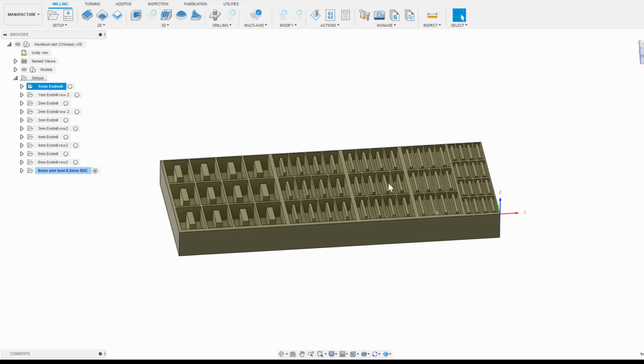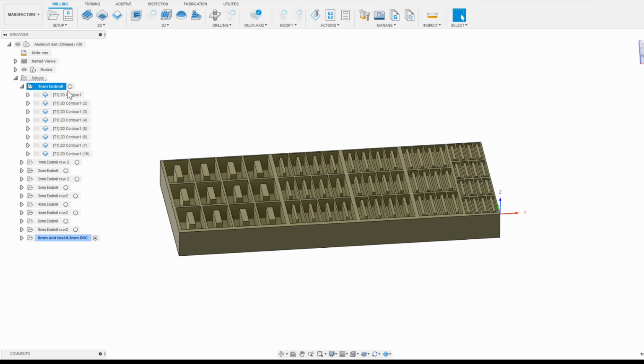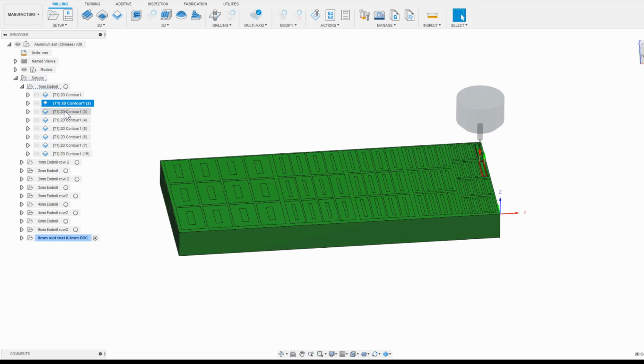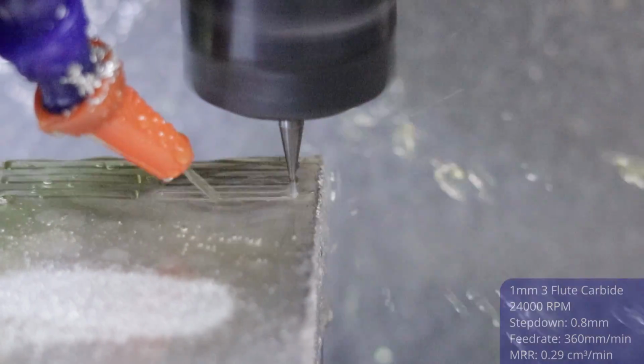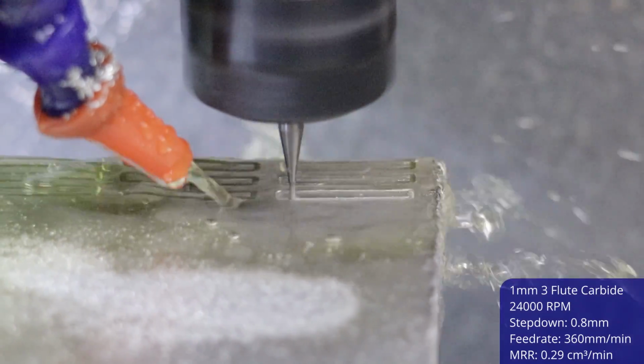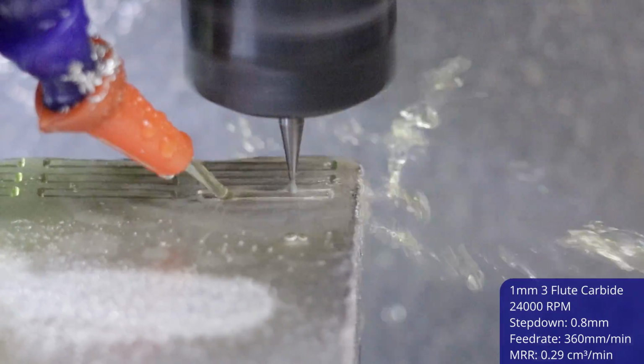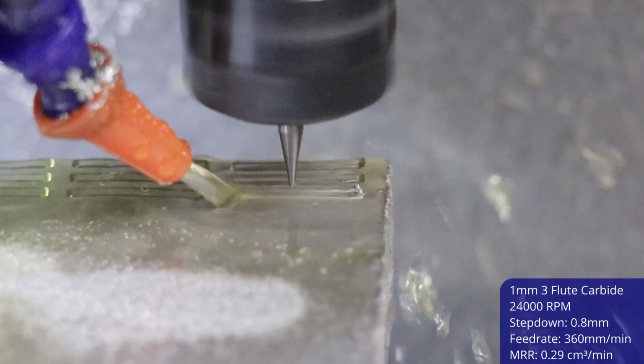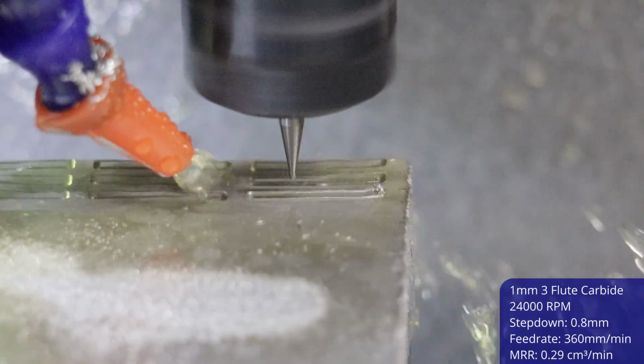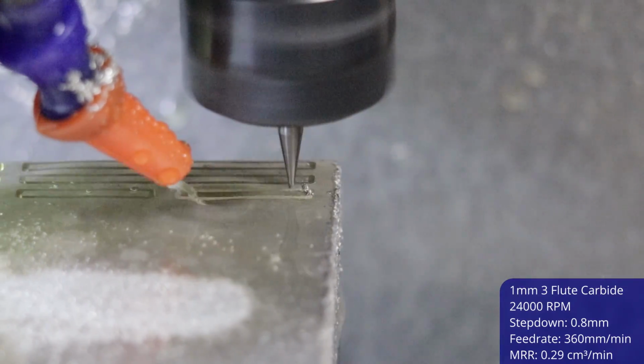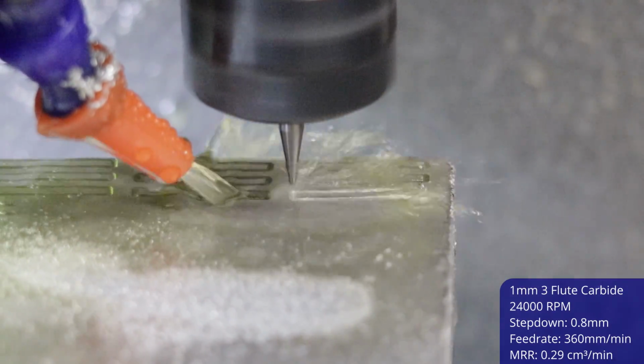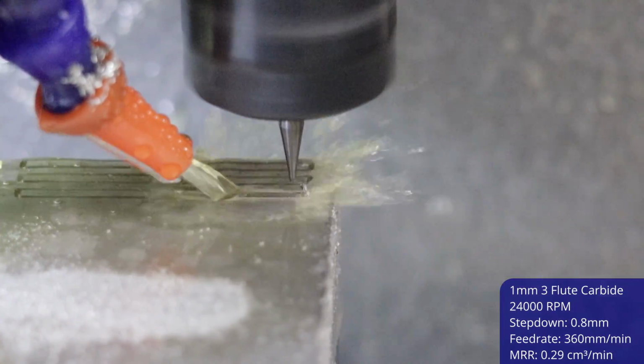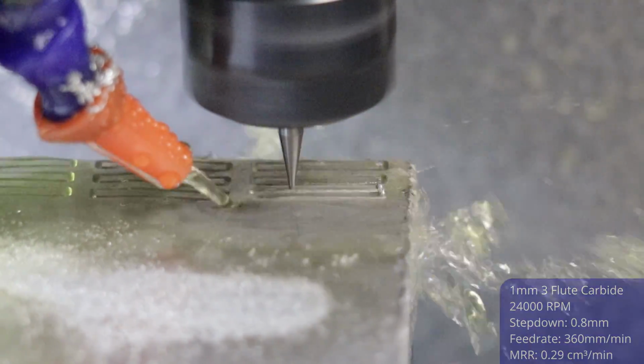I started off with a chunk of aluminum, and I did a bunch of test slotting with each of the smaller end mills. Again, I'll show you basically the final results of how hard I could push the tools and the machine. I am running the tools a little higher than the recommended surface speed, but they seem to be holding up fine. So with the 1mm tools, not much to see or hear again, and the tools break without a sound, so you really need to be careful not to feed them too hard.